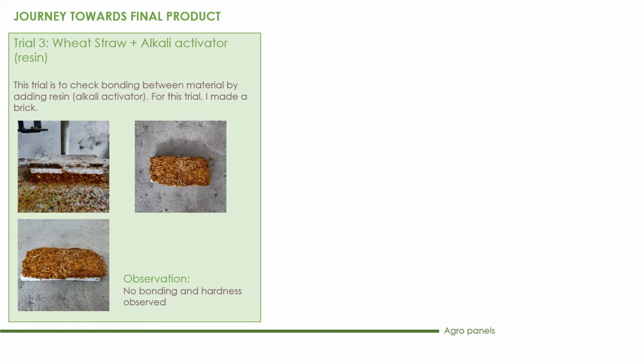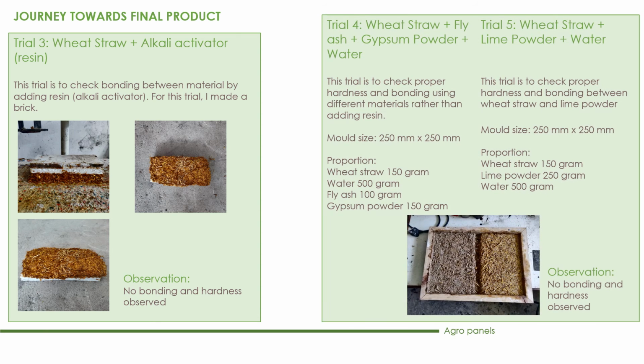Trial 3 was to check another bonding agent. Resin alkali activator was added, but this also resulted in insufficient bonding and hardness. Further trials included adding cementitious material such as fly ash, gypsum powder and lime powder along with the water, but this also resulted in similar failures.